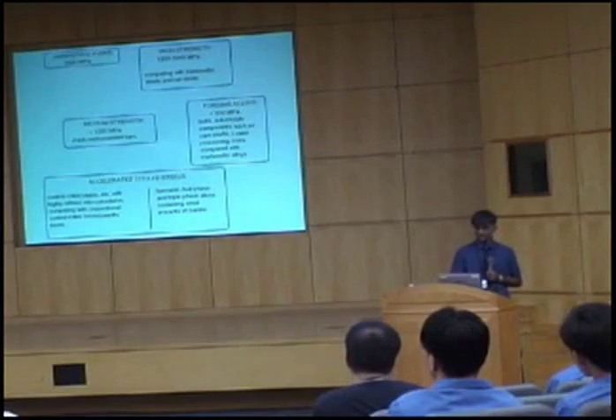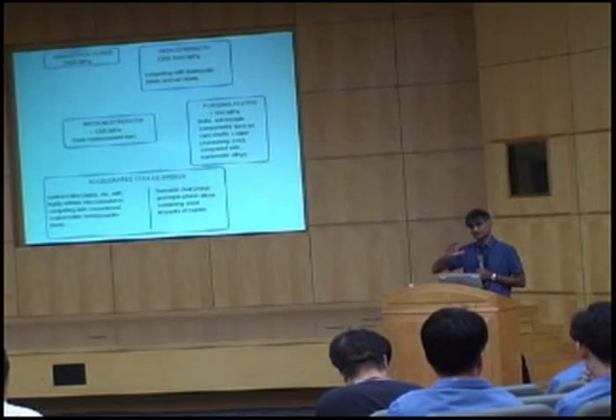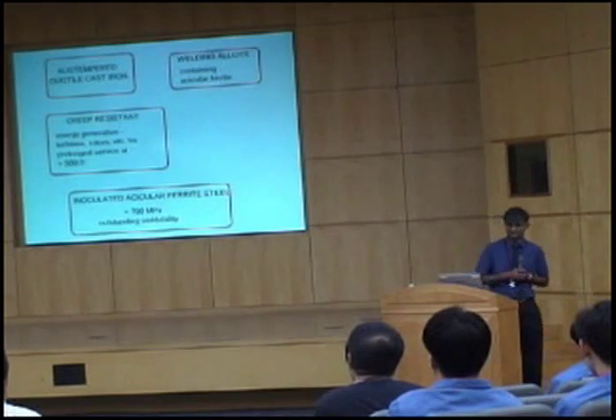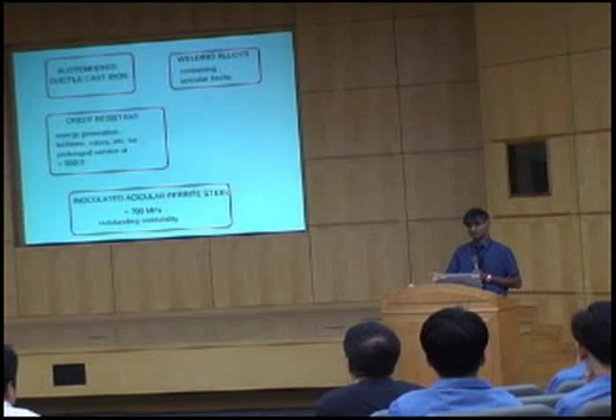If I now go on, these are all steels which are cast and then rolled and deformed and so on, but there's a large number of cast alloys which are used widely. So for example, the austempered ductile cast iron has a matrix which is bainitic ferrite and retained austenite. They have very good ductility compared with normal cast irons. There are many welding alloys which rely on bainite. Almost all the power stations which were built more than 10 years ago contain bainitic steels, the 2¼ chrome, 1 molybdenum type bainitic steels which resist creep.